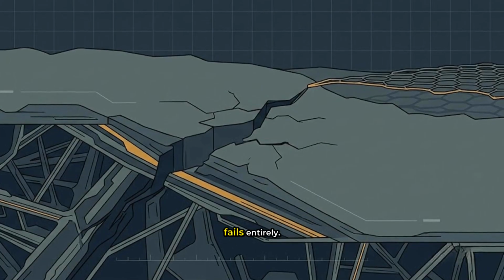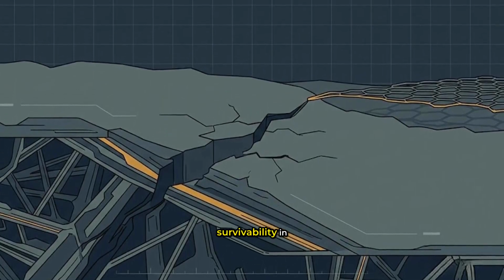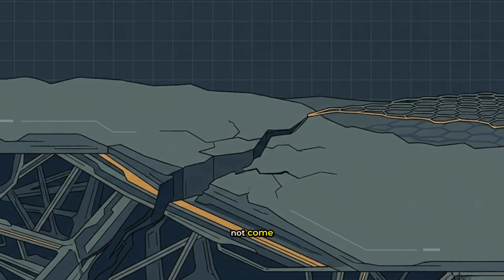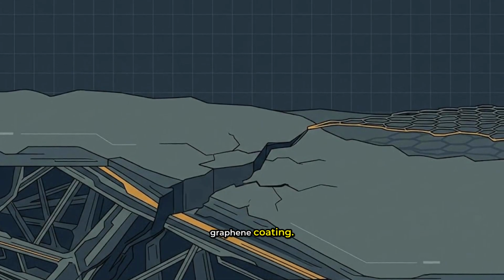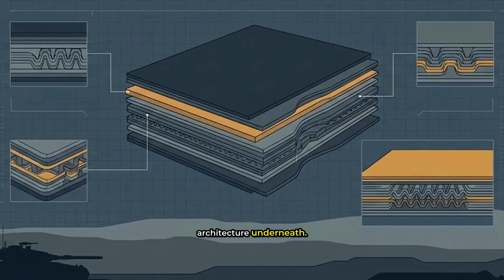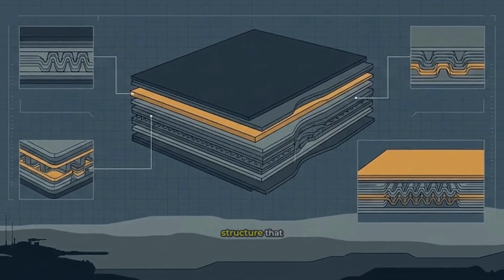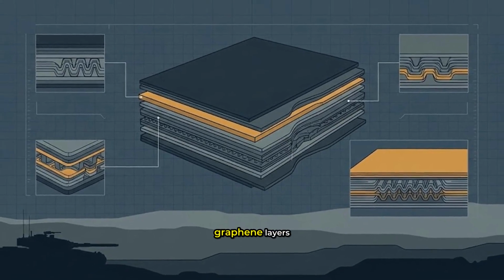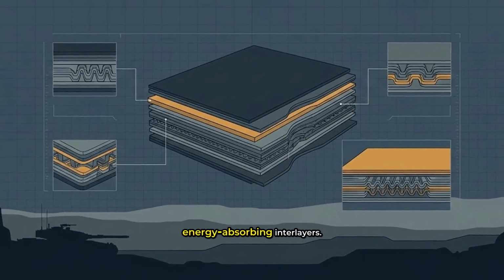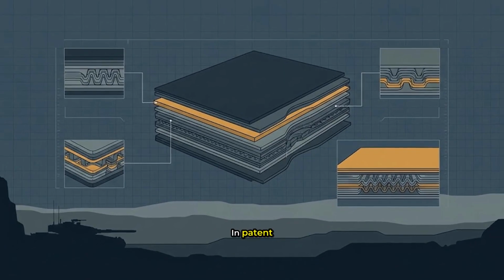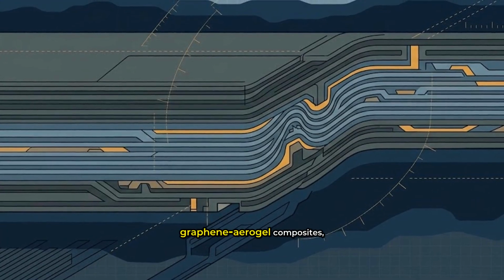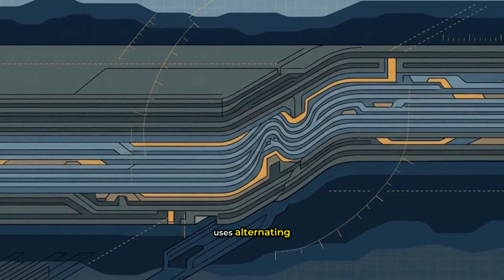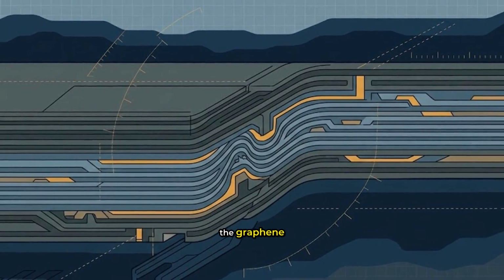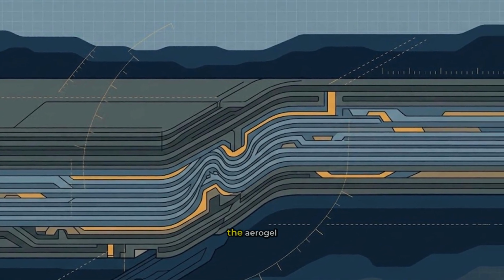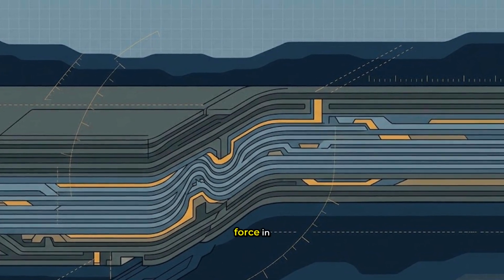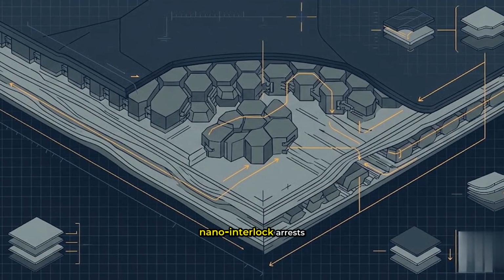The real survivability in a bird strike does not come from the graphene coating. It comes from the architecture underneath. The multi-layered structure that alternates stiff graphene layers with softer, energy-absorbing interlayers. In patent filings for graphene aerogel composites, the design uses alternating layers where the graphene provides tensile strength and the aerogel disperses impact force in a broad cone. That nano interlock arrests micro cracks before they can run.